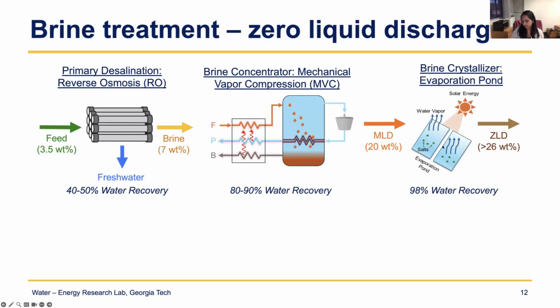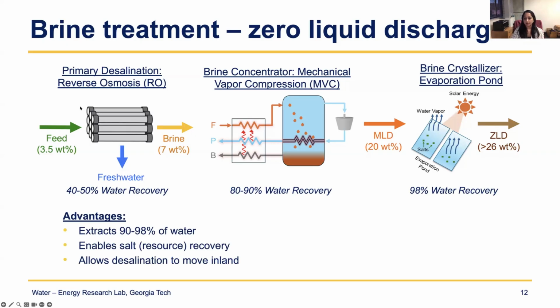And then finally, you can put that, let's say, in an evaporation pond and just allow the remaining water to evaporate under the natural sunlight till you get to the saturation limit and the salt precipitates out. This is how it's conventionally done. This is called zero liquid discharge because you've taken out almost all the water, over 98% of the water, and you're left with a very concentrated stream of minerals like salts of interest, as well as critical materials like lithium and some rare earths.